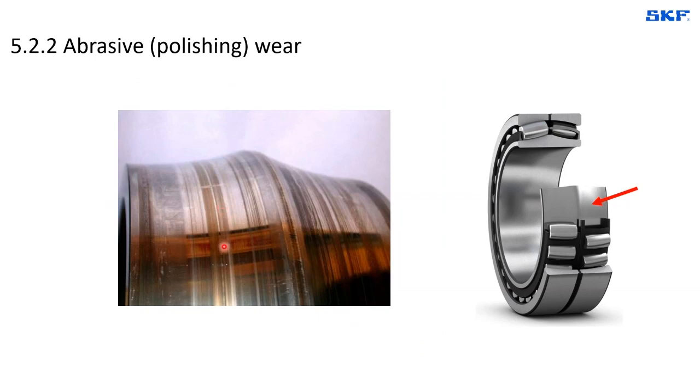So one of the things that this is teaching us is that the surfaces will, in some cases, under poor lubrication conditions, have a lot of metal-to-metal contact. So initially, the surfaces tend to polish themselves. So the roughness seems to be even lower than the original manufacturing range.